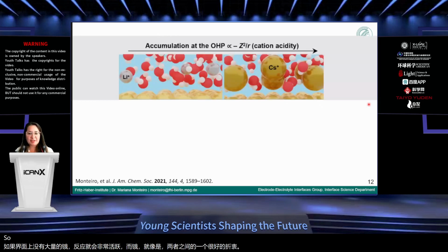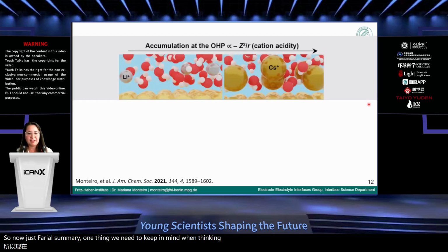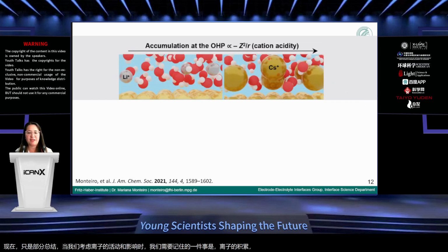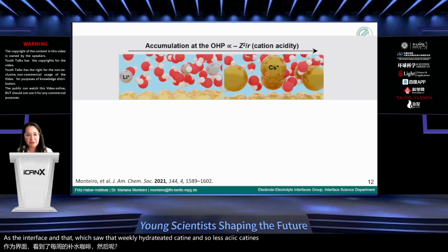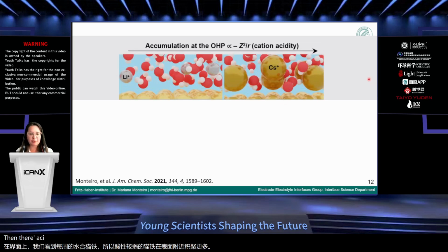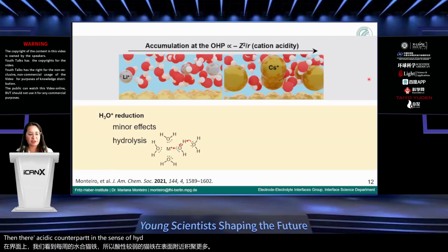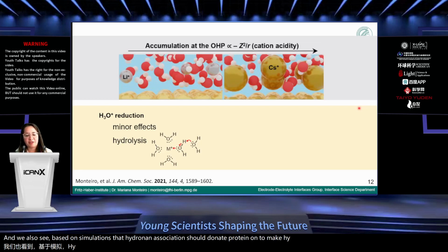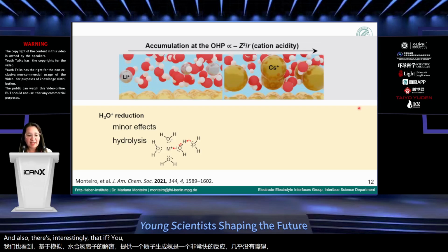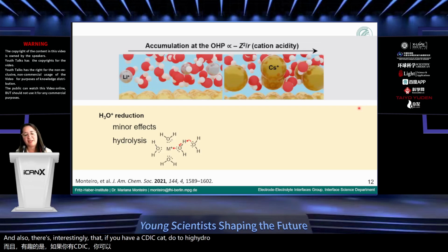So now just a partial summary. One thing we need to keep in mind when thinking about activity and the effect of ions is accumulation at the interface, and we saw that weakly hydrated cations, so less acidic cations, accumulate more near the surface than their acidic counterparts. In the case of hydronium reduction, we see very minor effects, and we also see, based on simulations, that hydronium dissociation to donate a proton to make hydrogen is a very fast reaction. It's almost barrierless. And interestingly, if you have acidic cations, due to hydrolysis, they discharge protons at the interface once the local pH changes.